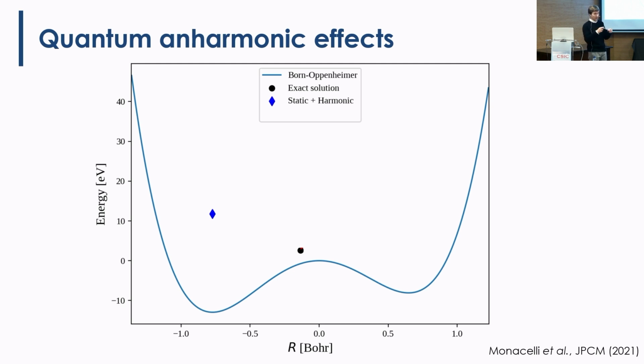Why quantum anharmonic? Because for anharmonic, you need the full shape of the potential to get that value. If you don't have the full anharmonic potential, you don't have that value. And everything that I have done in the last basically 10 years is to develop an ab initio method to get these kinds of things correct with the full interacting anharmonic theory, and that's why we've been kind of relevant here. So we developed the SSCHA method. It's a method to get these calculations done for solids. And when we apply this theory, that's the energy we get. It's very close to the exact energy, and the positions of the ions are also very close to the real expectation value of where the ions are. So that's why we have a good theory here to treat these materials, right?